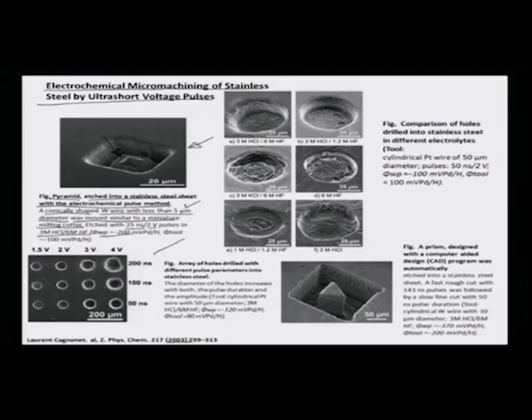This again is another illustration of the process capability related to ECMM. You can see for pulse durations varying from 50 nanoseconds to 200 nanoseconds, there are different hole diameters in the range of close to about 30 to 50 microns, which are obtained at different pulse magnitudes. So this is an array: 4 volts 200 nanoseconds, 3 volts 200 nanoseconds. These are the different hole diameters being made with the different voltage and nanosecond combinations. In this case, the tool was a cylindrical platinum wire, okay, and that had a tip diameter of 50 microns, and the reported values here indicate what kind of electrolyte was used. It is again an HCl hydrofluoric acid combination, and the workpiece potential and the tool potential are rated as minus 120 and minus 80 millivolts with respect to a standard hydrogen electrode.